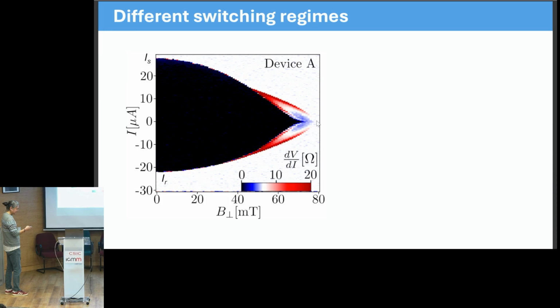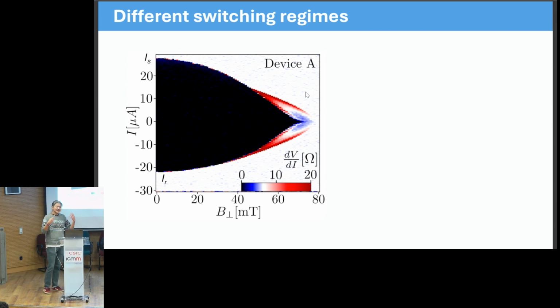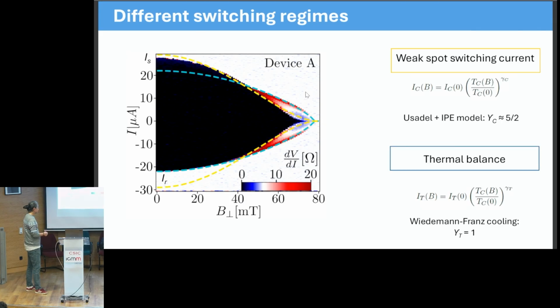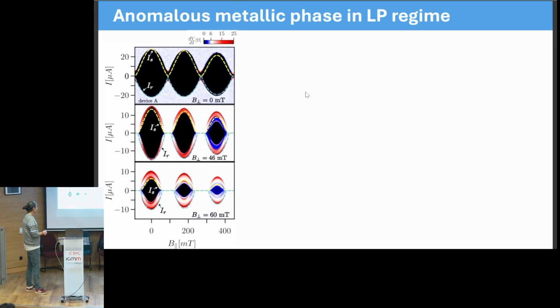So very shortly here, so I don't take too long in this part, what we study here is how the switching current changes as we try to weaken the superconductivity by applying magnetic fields. We observe that the physics of this transition in devices like this is dominated by this inverse proximity effect and then by heating effects that are related to when parts of this nanowire turn normal. Okay, so we understand this quite well. I will just go a bit quickly over here.